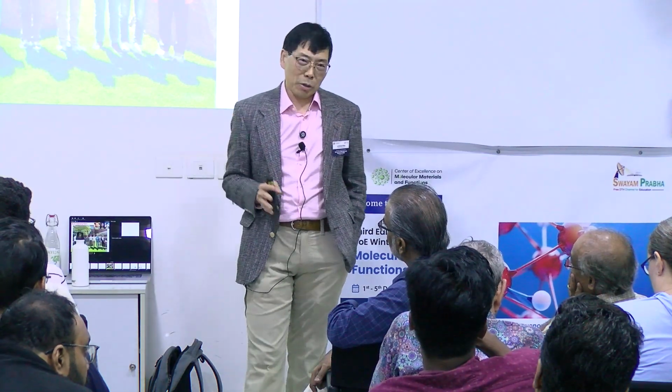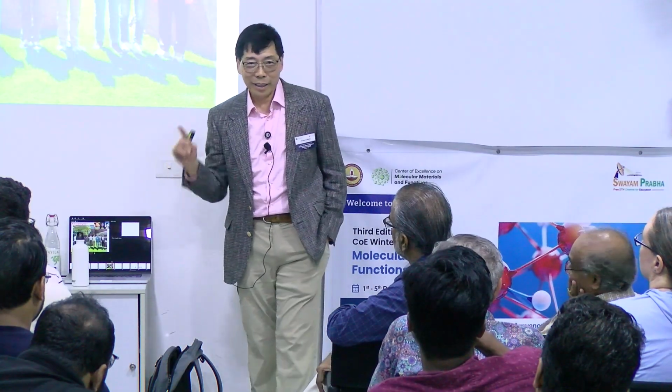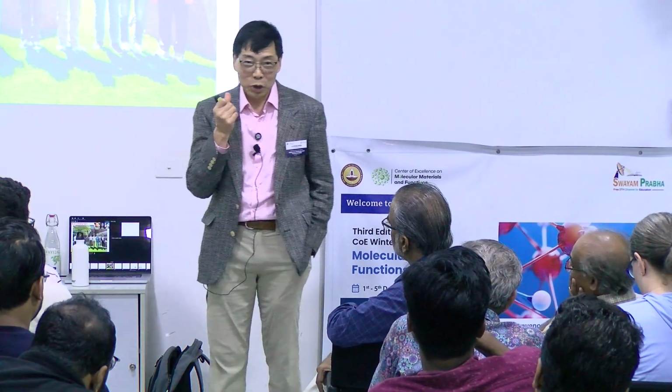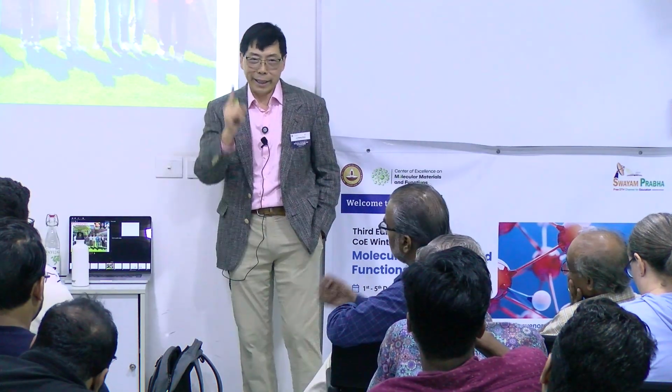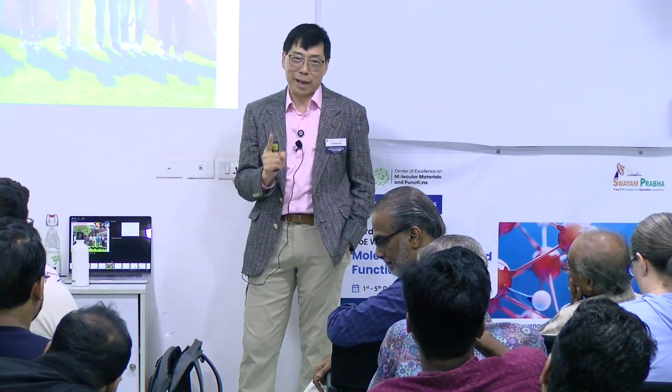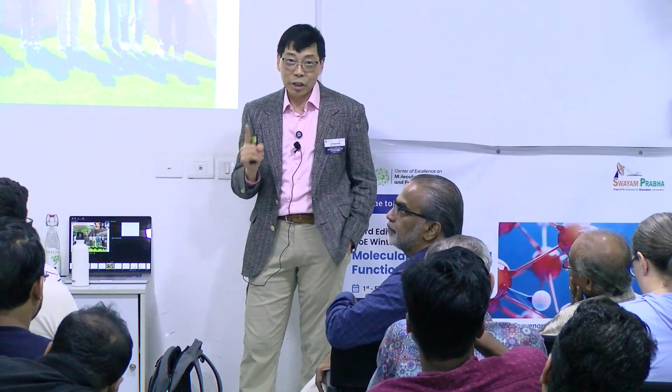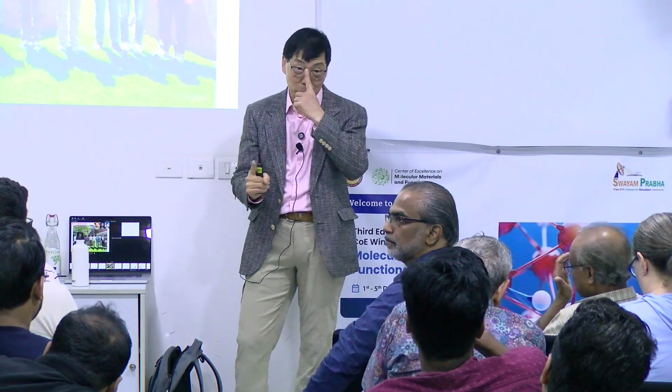No, the hydrogen is gone. There's no question it's gone. We can't detect it. It's not in the mass spec. It's not in the NMR. So we know that the hydrogen is gone. It's metastable. As I mentioned, even while we are taking the NMR spectrum, during that time scale, hydrogen is coming off. So the hydrogen is metastable, there's no question. For the tetrahydride, it's metastable. For the trihydride, it's stable. It's very stable. The tetrahydride is metastable.